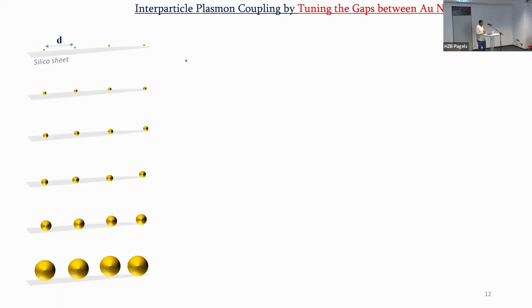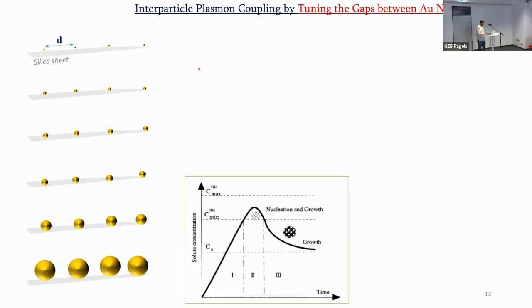And then the hypothesis was, in my next cycle, I will maintain a synthetic condition such that you will be below the nucleation. The concentration of the gold precursor will be below nucleation, so that there will be no more nucleation once you have the nuclei on the first sheet. And you will only have a growth stage. So what will happen? All the gold atoms that you produce in your synthetic reactor will go and grow the existing seed, the existing gold nanoparticle. And that way you keep growing the gold nanoparticle, and that will reduce the distance d between them. So that was the hypothesis.